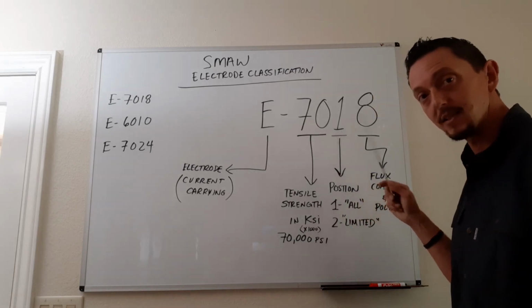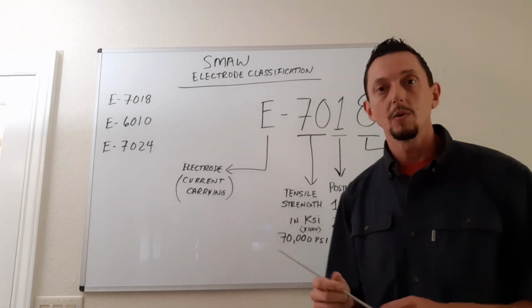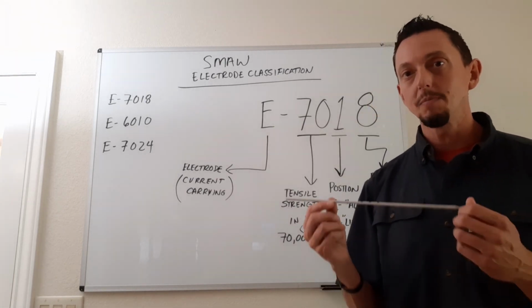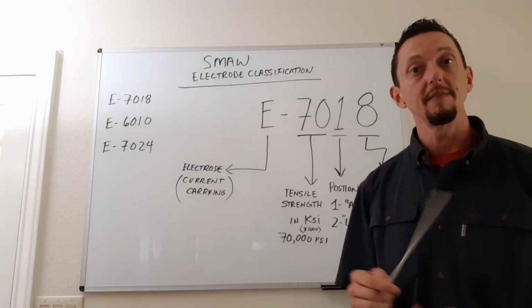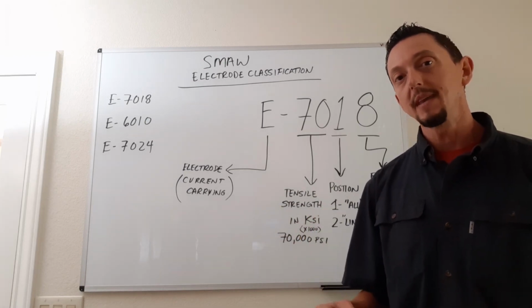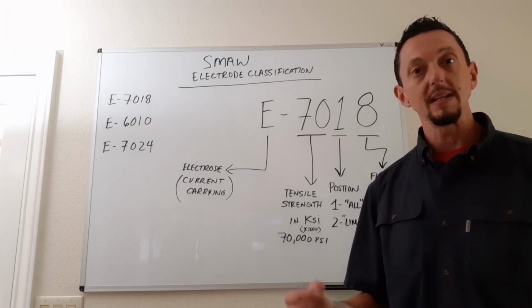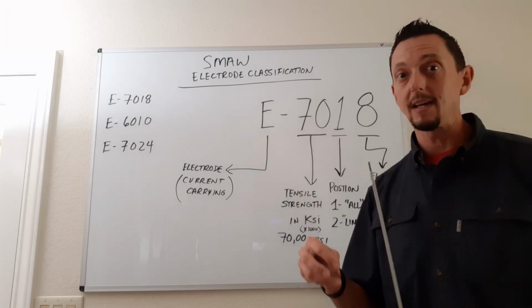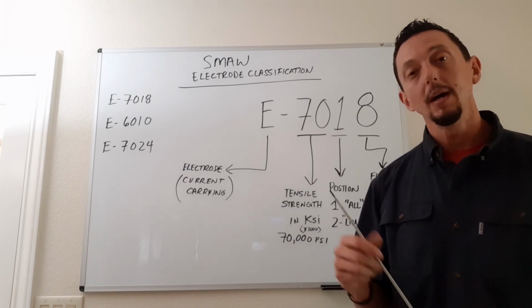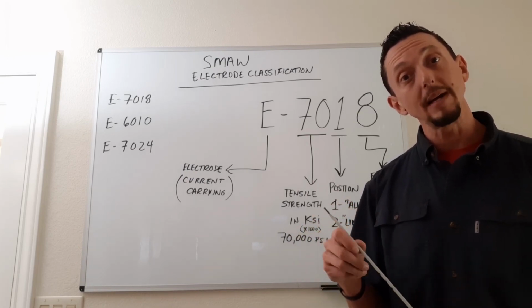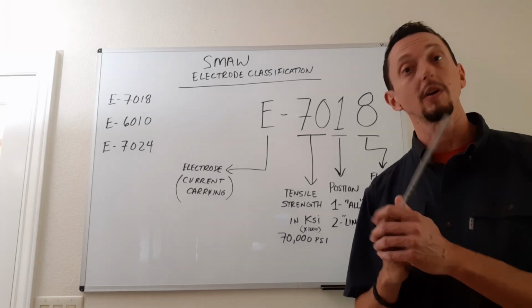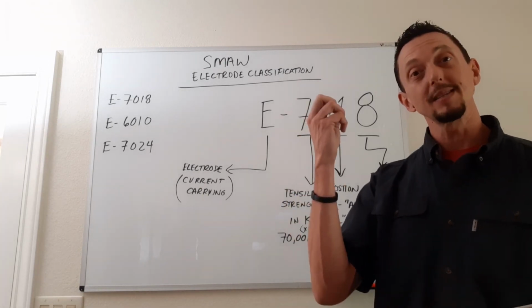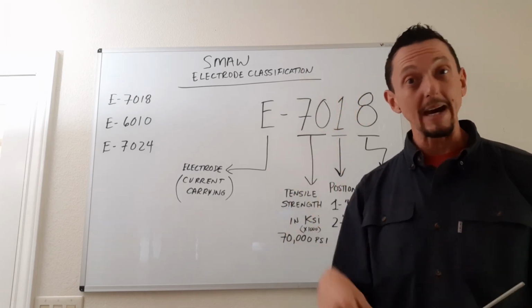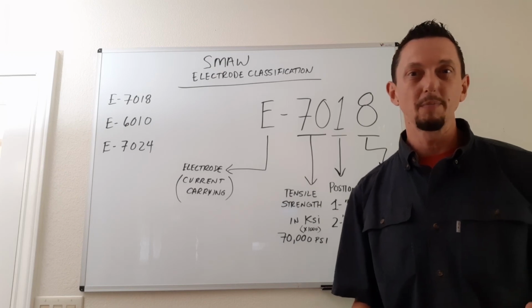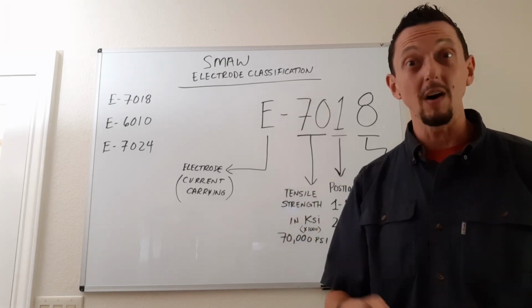The next digit here has to do with the position that it can be used in. So different electrodes are designed to be used different ways in terms of the positions that they can be used in. Some of them are what's called a fast fill, which means that it's designed to fill the weld pool as quickly as possible, but typically those are not meant to be used out of position. You can't use those vertical up or overhead typically, right? Because it's fast fill, the weld pool doesn't cool fast enough and it will drip down, either produce a weld profile that's unacceptable or just fall out, right?